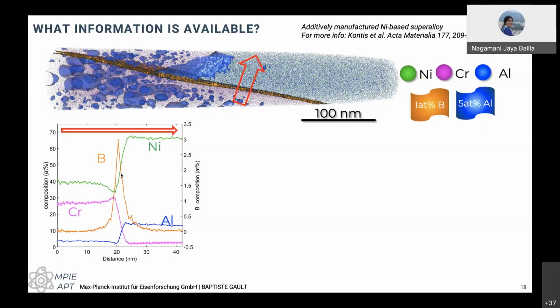So here I have a big cylinder that I've positioned normally to the interface. I think it's about 40 nanometers across, and I'm putting it through the interface, and then every 0.1 nanometer, I put a new bin, and then I count how many atoms of all of the species I have in 3 dimensions. And then I add 1 point to the profile, and then I move to the next bin, and I do the same measurement. So that's what we're seeing here. And that's why you can see there are error bars, and they're very tiny because I count quite a lot of atoms. So statistically speaking, I'm making a measurement that's not too wrong.